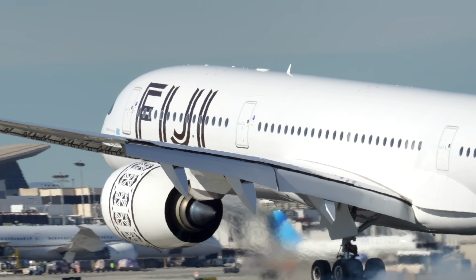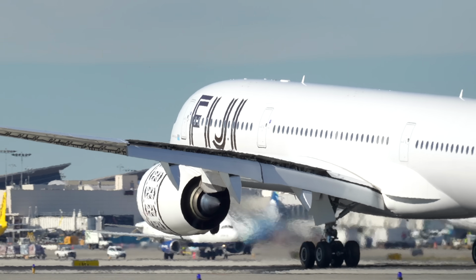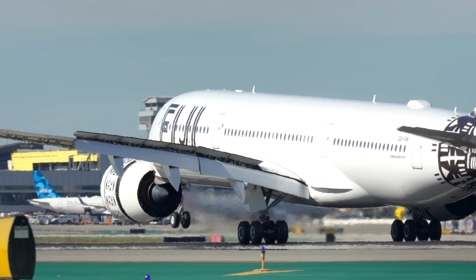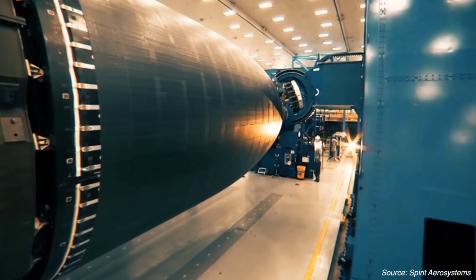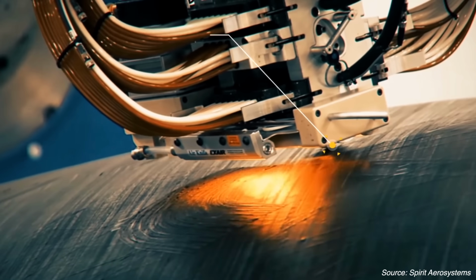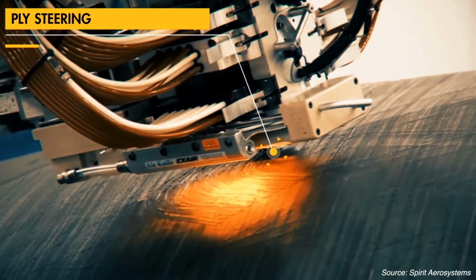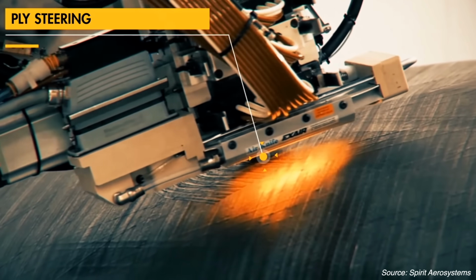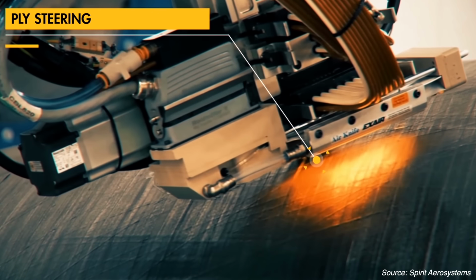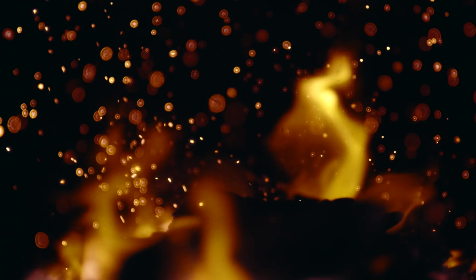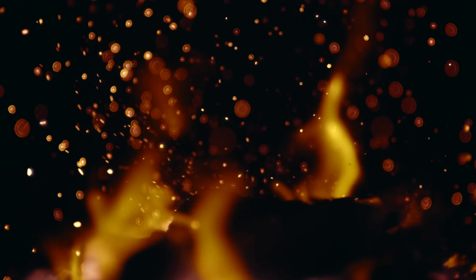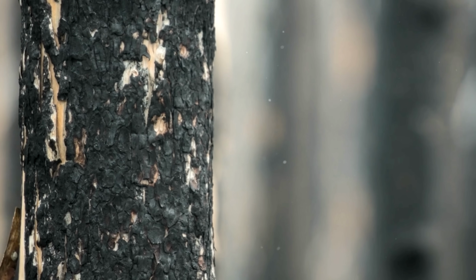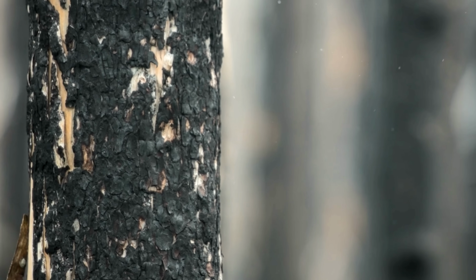Moreover, when CFRPs are exposed to extreme heat, they tend to burn in a rather complex way. Remember, CFRPs are made of layers of carbon fibers that are bonded together by resin, and this creates distinct strata within the material. When the outer layer burns, it tends to char, which can actually form a protective layer that'll slow down the progression of a fire.